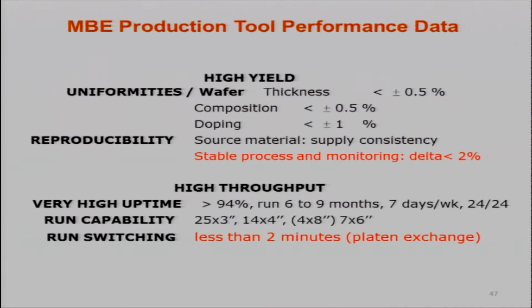Now, this MBE production system is very uniform. The uniformity of the thickness is 0.5% across the wafer. And then very stable. The most important thing I want to show you is the very high uptime, 94% uptime. The run is you can have 6 to 9 months of running before you open the MBE system. It runs 7 days a week, 24 hours a day. That continuous running, you can run 6 to 9 months without opening the system.